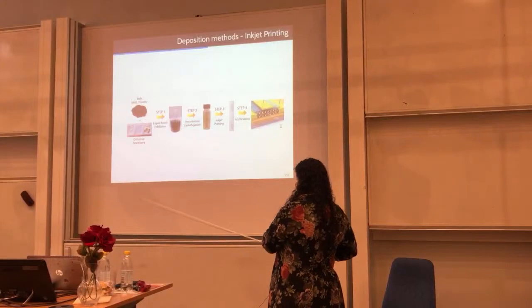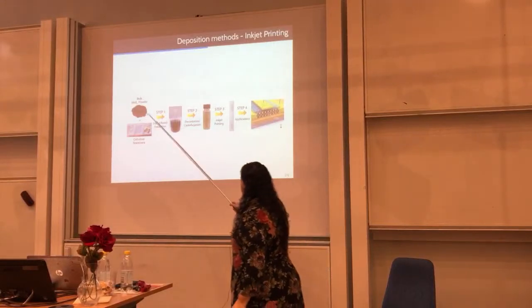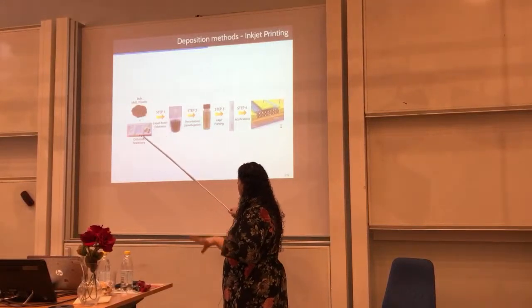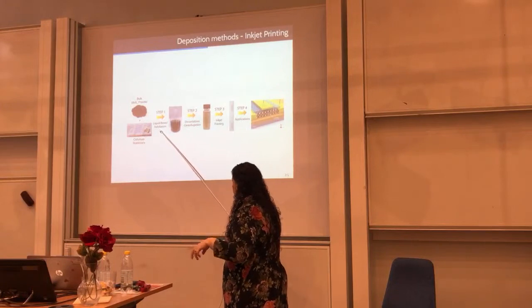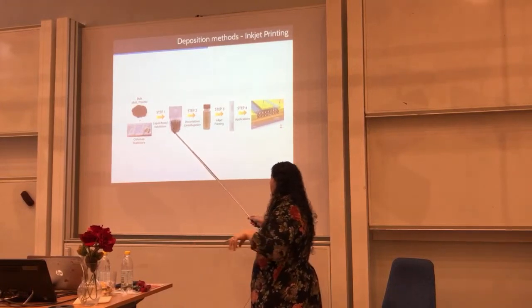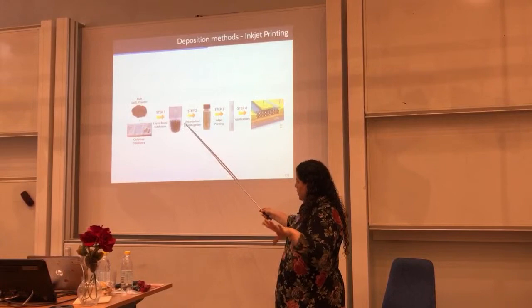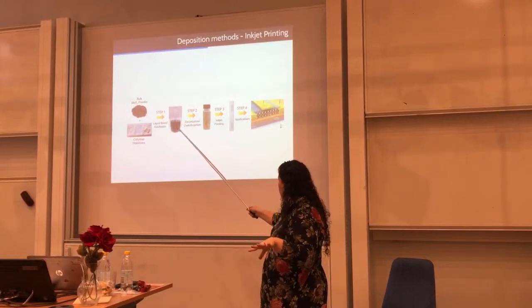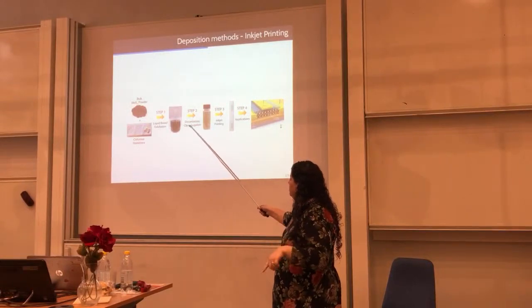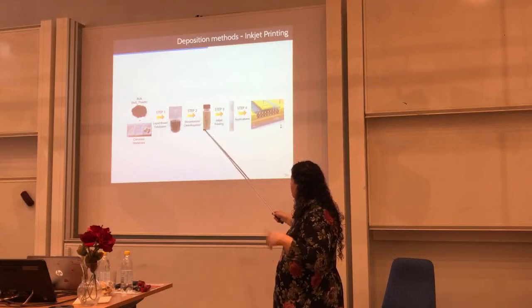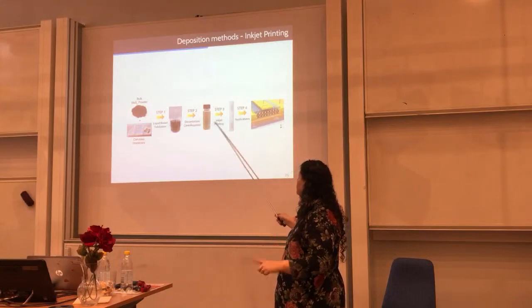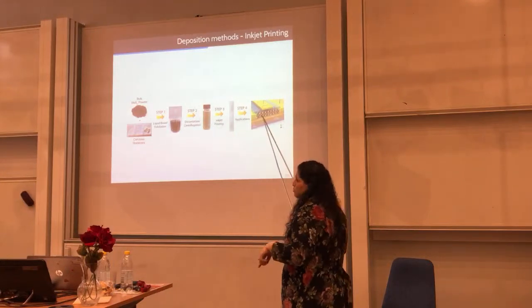So to sum up, you have your materials, the bulk powder and the stabilizer. You do the liquid phase exfoliation. You get a dispersion. It's very black. There's a lot of material that's not individualized here. You need to decant and centrifuge. You end up with a slightly clearer dispersion that you can use in a printing head. And then you can build a device.